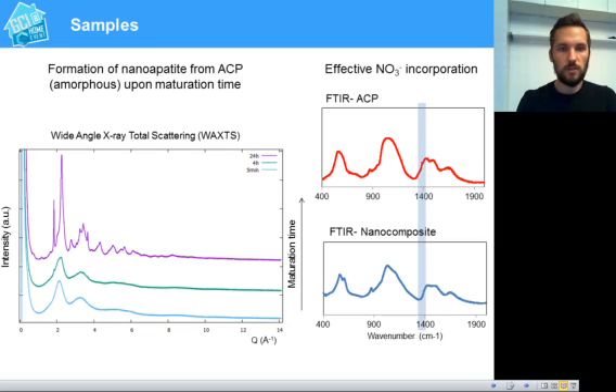And this is clearly seen with the wide-angle X-ray total scattering experiments, where you can see a completely amorphous trace at the bottom for the amorphous material, transforming progressively into apatite after 24 hours. No other phases were detected, so the nitrate detected by infrared spectroscopy and elemental analysis is actually incorporated into the material or adsorbed at the surface.